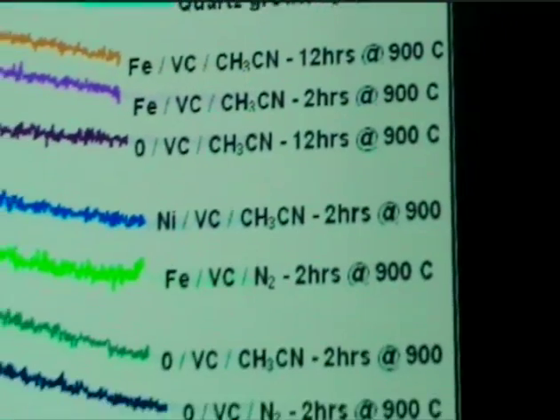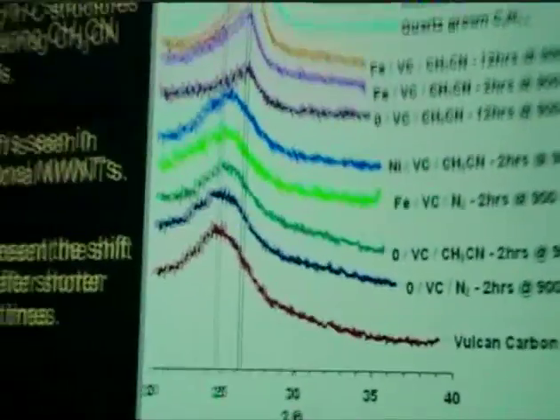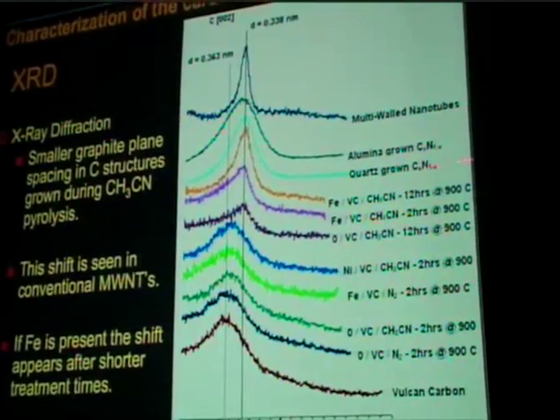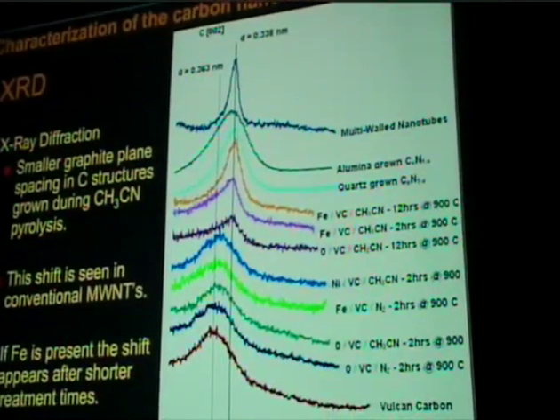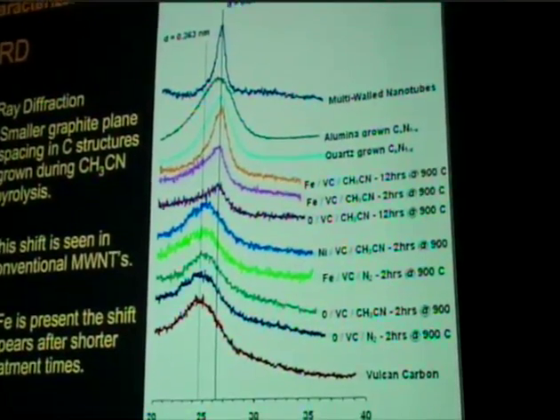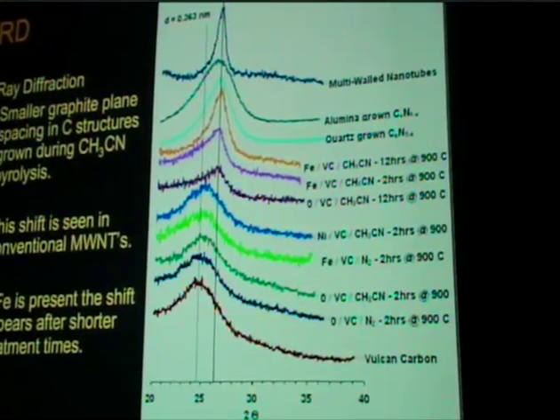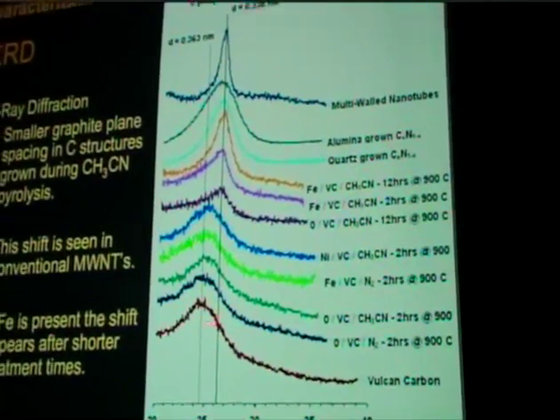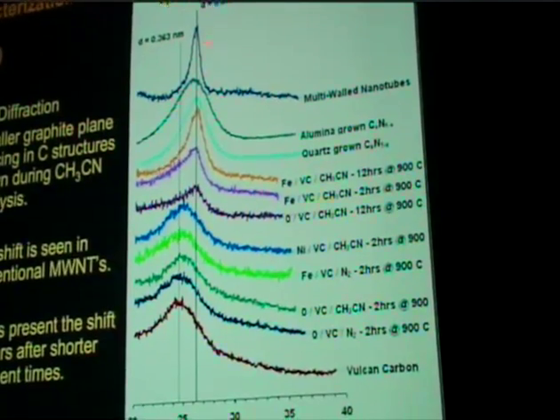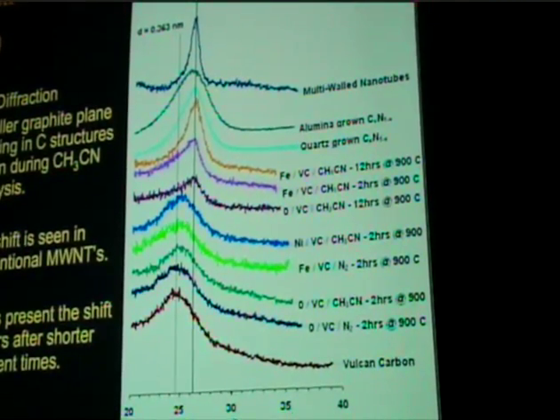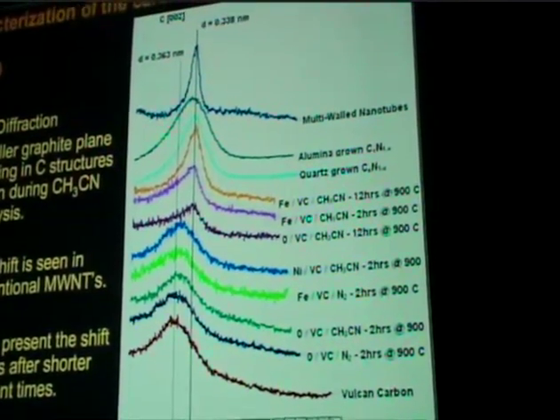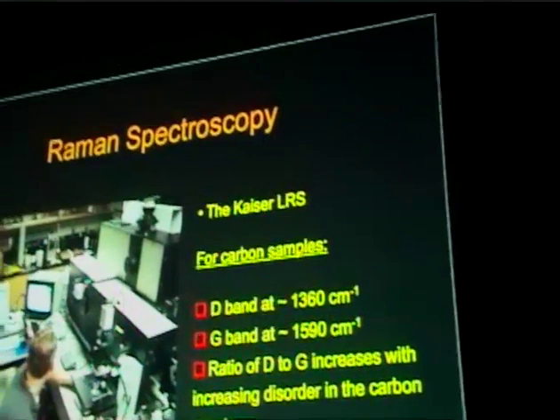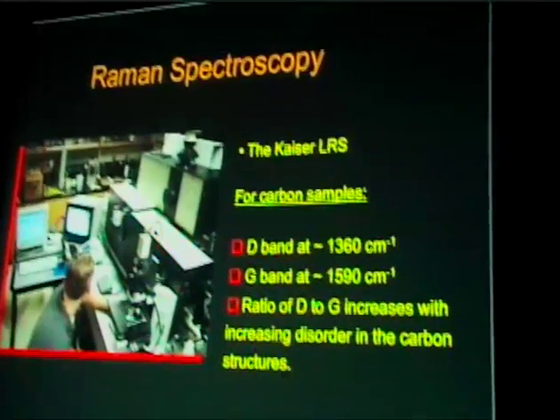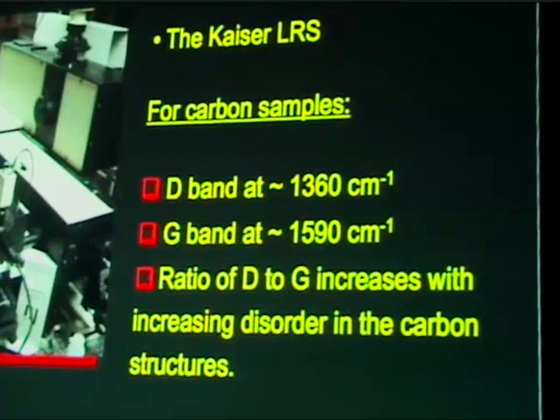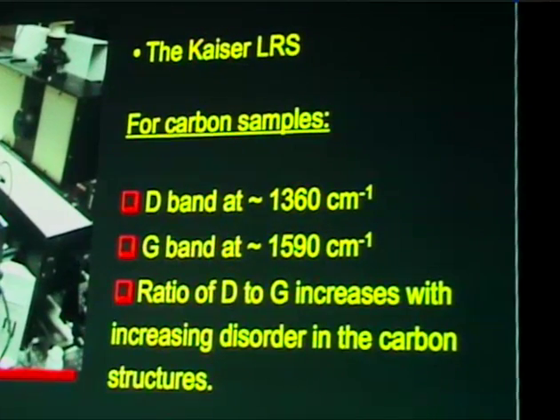And this shift is also seen in multi-walled carbon nanotubes. And if we have iron present on the support, this shift appears after shorter times. As you can see here, here's the Vulcan carbon, and we're getting closer to the d-spacing that's seen in multi-walled nanotubes. Raman spectroscopy, again, has typical bands for D and G bands.